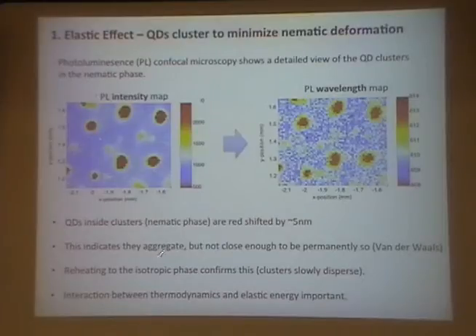So they are aggregated. If we heat back up to isotropic, they start to drift apart again. Why? This is consistent with the idea that their ligands are interdigitated. The particles themselves are not so close that they'll never come apart. It's more like there's a thermal aspect to it. If we heat them up, the ligands can release from each other and the cluster will slowly start to disperse apart. The kind of redshift that we get is consistent with that. We can also see it under the microscope, where they gradually diffuse out.